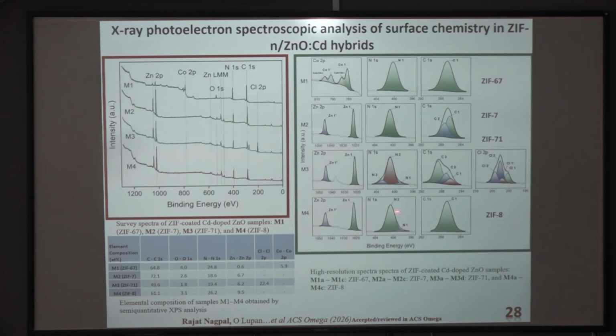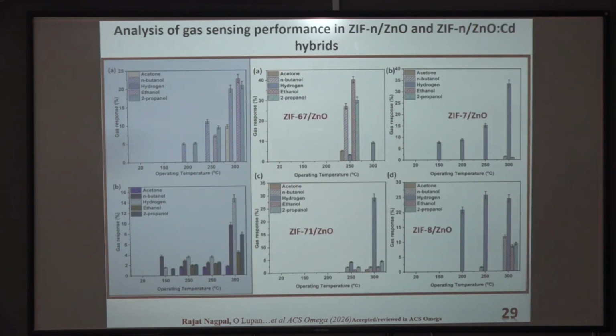Among the hybrid system, XPS spectra give chemical information in these photoelectron lines for metal. We can see it confirms a 2+ oxidation state for the metals, and about the chemical bonding environment, for instance, nitrogen has three different chemical bonding environments in M3 case and 2 chemical bonding environments in M4. And about the spin orbit splitting, we can confirm it using Cl 2p based photoelectron lines.